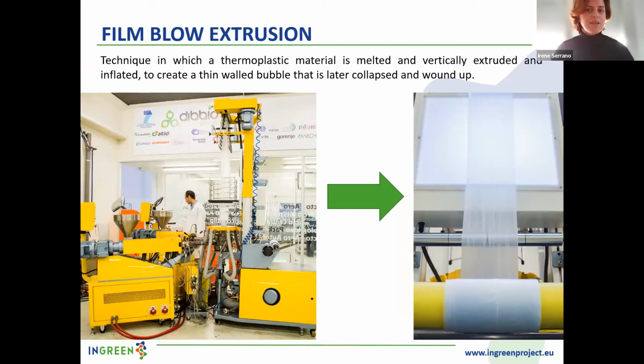Once the compound is obtained, the next step is the film production. Film blow extrusion is a transformation technique in which a thermoplastic material, or compound in this case, is melted and then vertically extruded and inflated to create a thin wall bubble that will be later collapsed and wound up. This is the step in which the suitability of the material to become a film is assessed. The compound in pellet form is fed through a hopper into a heated barrel that has 1 screw rotating inside, and the material melts by action of heat and shear as it did in the previous step until reaching a viscous state.